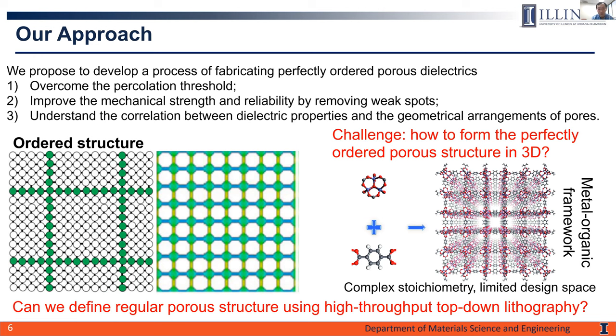Here we can do it based on materials like metal organic frameworks, or MOF materials. There are some existing works in this direction, but the problem with MOFs is they have very complicated stoichiometry and their synthesis requires not only high temperature but, in many cases, high pressure. So they're not compatible with the back end of line integration process at all. The metal ions and organic linkers in these MOF molecules may also not be compatible with silicon CMOS technology. And for MOF materials, we also have a very limited design space regarding the size, the shape, and the arrangement of those nanopores.